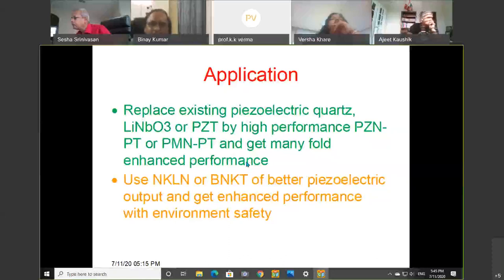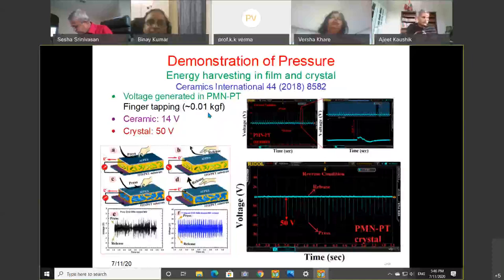And we can put a ceramic directly also. This diagram shows a nanogenerator, but these values are not for this. These values are when we are using directly a ceramic or directly a crystal as a bulk. If I put a pressure on this, these results pertain to this figure. You can find that if I am using a PMN-PT ceramic, we are getting almost 14 volts. And if I put a PMN-PT single crystal directly, without any contact or any polishing or doing anything, just put a crystal and apply pressure by hand, we are getting almost 50 volts.